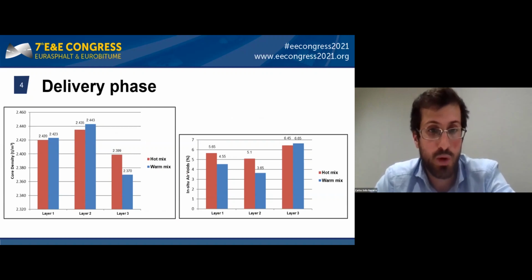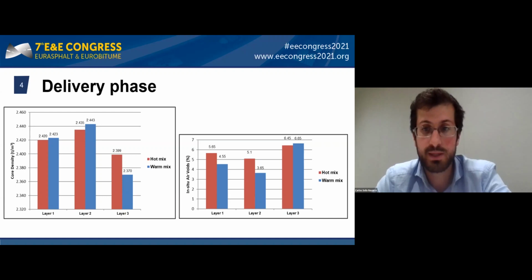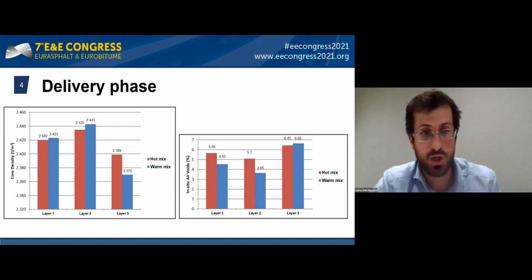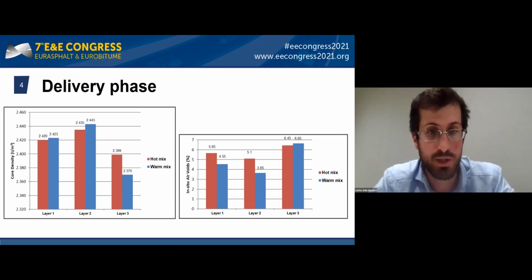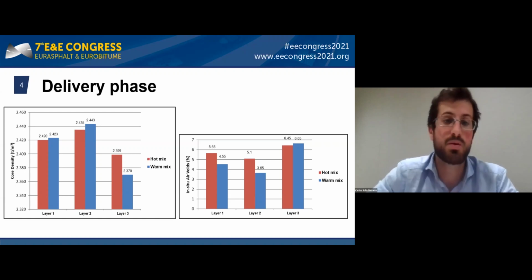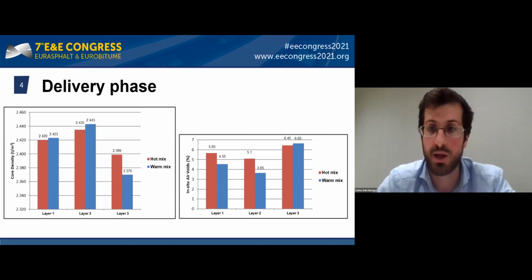We undertook a trial with hot mix and warm mix in the same section with the same conditions, and we had similar results in terms of compaction, relative compaction, and densities. So all of that as expected.